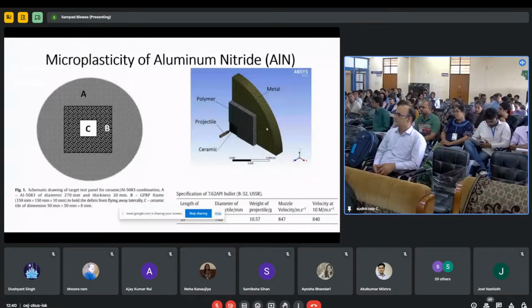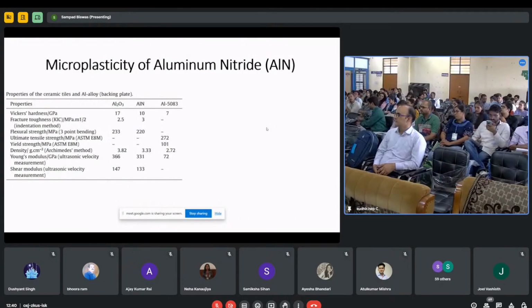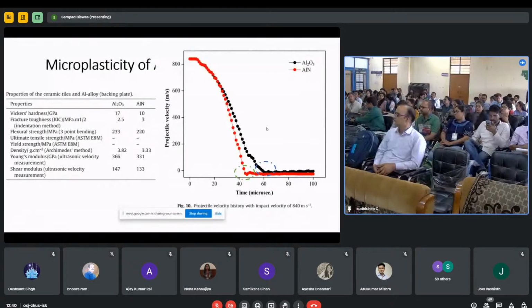Now what I wanted to show you is that when the projectile is hitting the ceramics, the projectile velocity gradually goes down. Because it breaks the ceramics, at the same time its own velocity is going down. So this can be simulated. This can be experimentally verified. This can be simulated as well. So we carry out the simulation work.